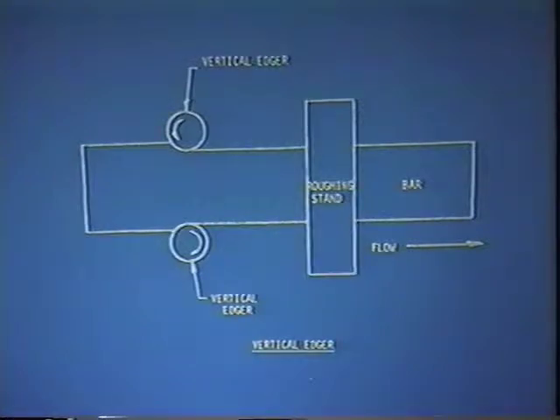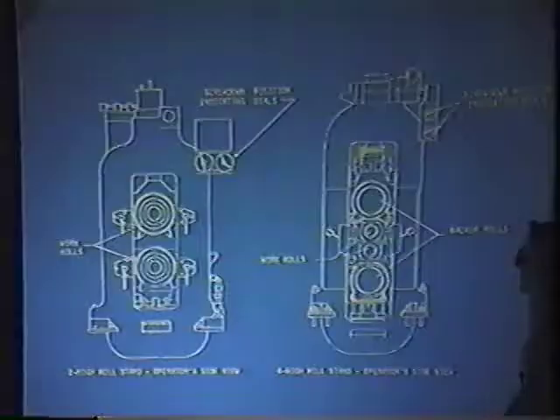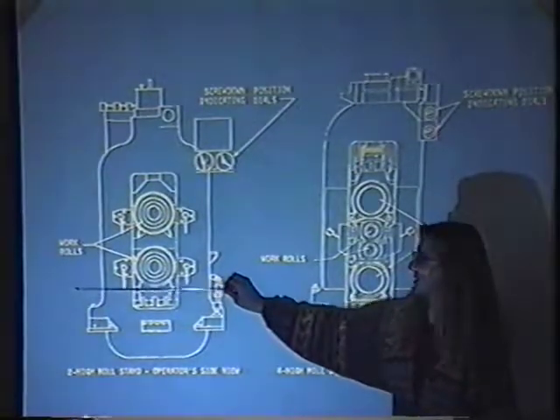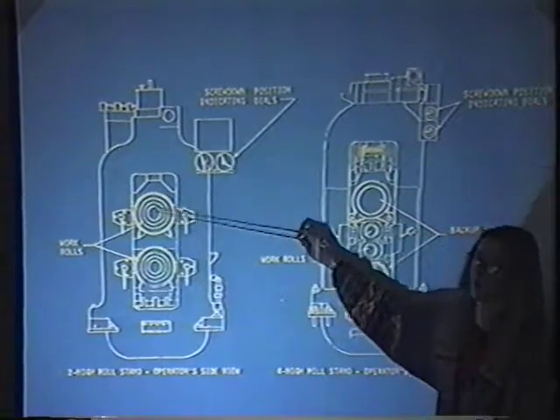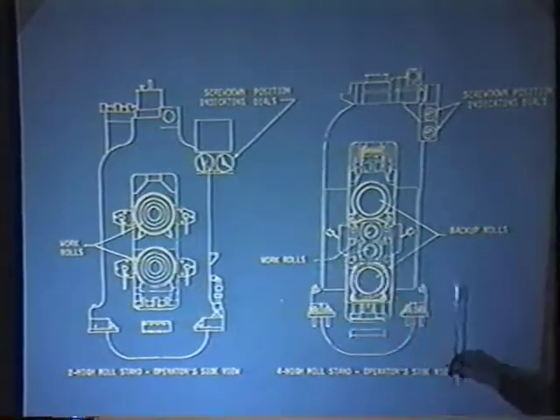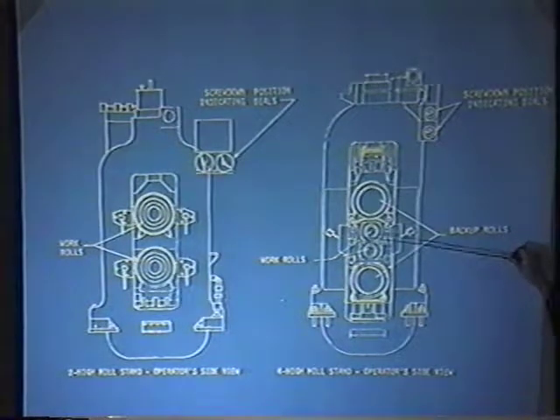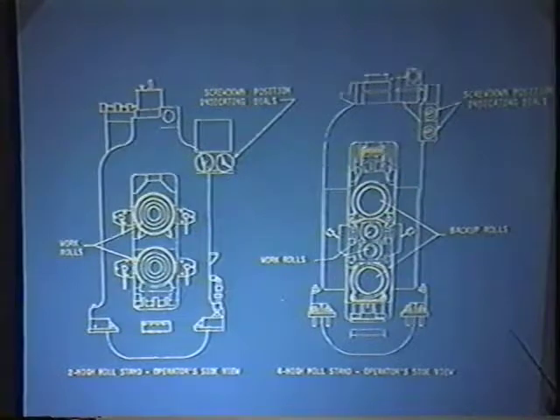And this is a pretty simplistic picture of what our vertical edgers do. Set the width before it goes through the stand. Now I said we have 5 roughing mill stands. The first 2 are what are called 2 highs, and the last 3 are 4 highs. And this is what we mean by them. R1 and R2 look like this. The floor level is right about here. So there's a lot of it that's in the basement. But there are no backup rolls on these 2 stands. Versus a 4 high stand, which has backup rolls to reinforce the work rolls, to make sure the work rolls don't deflect when they're trying to take it down to that final dimension, down to 1 1/4 inches.